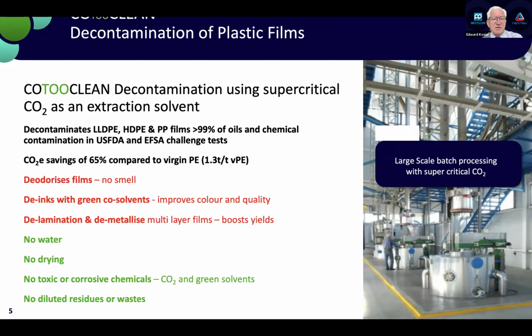The decontamination process extracts all volatiles and semi-volatile materials, which means that the recycled films have no odor and no smell, which is often a feature of other recycling processes. We also can see that the technology can remove inks when we use green co-solvents with the CO2, and those solvents can be recovered. These are non-toxic solvents, things like alcohols that are widely used and other similar materials. This way we can remove inks, which improves color and quality and also reduces toxicity issues.